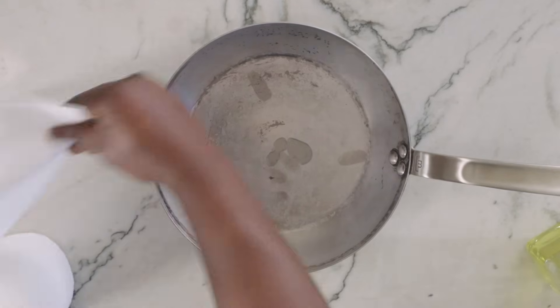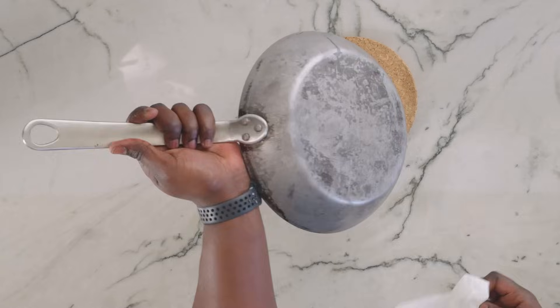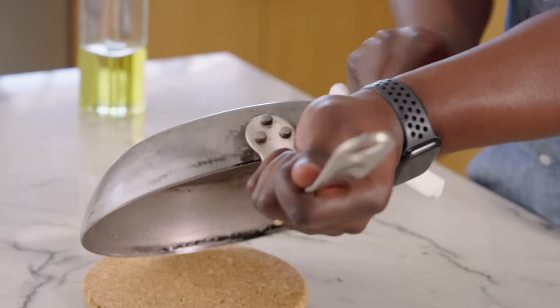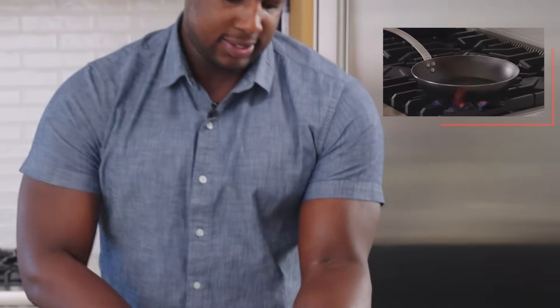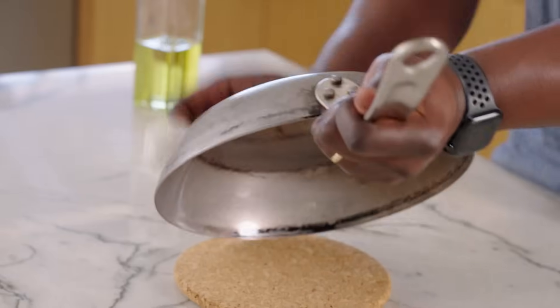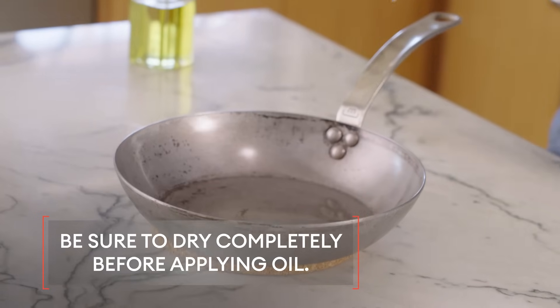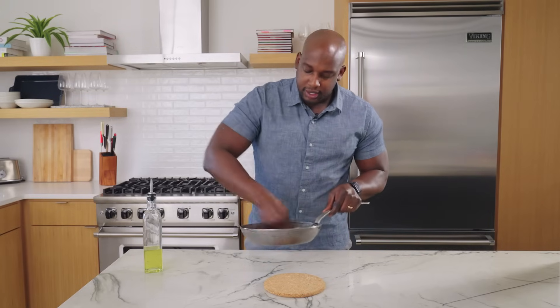Add just a very little bit of grapeseed oil, and we're going to coat the whole pan — all of it needs its coating. We're only using a little bit of oil here; too much oil will get us a sticky mess, so just a light layer will do it. I'm going to do the stovetop method — it's my favorite, it's quick and efficient. One thing I do want to note: I went ahead and dried this completely. I put it on the stove on low to medium heat to evaporate any water I couldn't see, because if water gets trapped underneath that oil it's going to cause more rusting. Make sure it's completely bone dry before you add oil.